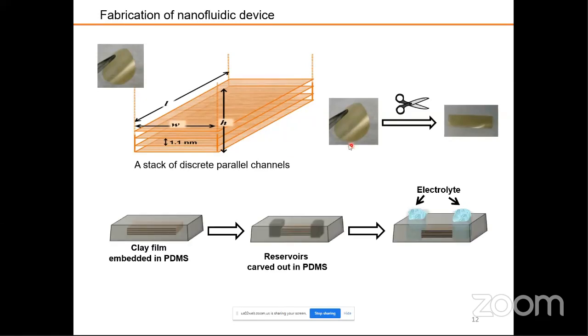Here we have made a device out of this freestanding film to study the transport behavior of ions through this confined space. We have cut this membrane into a rectangular piece, put it inside a PDMS film, which is a hydrophobic material, dug some holes at both ends and put in our electrolyte. Whichever ion's conductivity we want to check through these channels, we can put the ions in both electrolytes, and then we can measure how they transport through these channels.